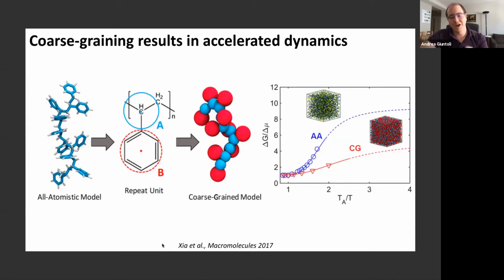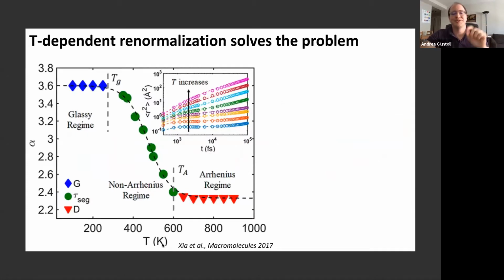So that's a problem that Professor Ketan worked on in the past years with his grad students, postdocs, and in collaboration with NIST. And what they did to solve this problem was to create some sort of calibration, this alpha parameter that can change with temperature, so that for every temperature, you're always able to match the dynamics between the two models. And to do that, they tailored it so that some specific quantities were matched between the two models.